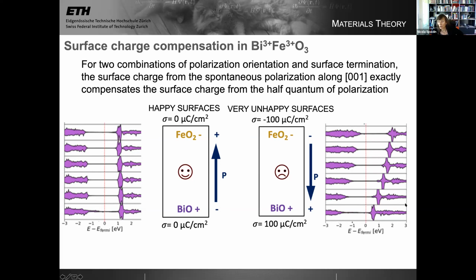This is what a ferroelectric usually looks like, a thin film of a ferroelectric. You see there's a strong internal electric field, which causes the bands to bend. You can also see that the top of the valence band starts to overlap the Fermi energy at the top, and the bottom of the conduction band at the bottom. This is making holes up here to try to compensate the negative charge and making electrons down here to try to compensate the positive charge. So this is a typical ferroelectric slab with the net polarization. In the happy configuration, there's no internal electric field because there's no surface charge.